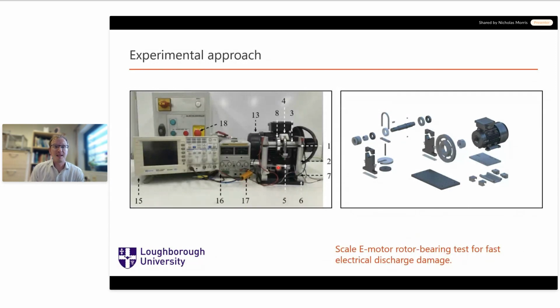So why do we want these particular loads? They're there to replicate the forces which act on an EV bearing. A typical EV rotor weight will be between 80 and 230 newtons, so 8 kilograms to 23 kilograms, roughly, from what's out there in current technologies. The bearings have to support that weight, but then you also have the acceleration of the vehicle, and the bearing has to keep the rotor moving with the vehicle as it accelerates around corners and decelerates and accelerates. And then we also have imbalances in the rotor, typically limited to about 2 G in millimeters per second, to prevent significant eccentric loading of the bearing.